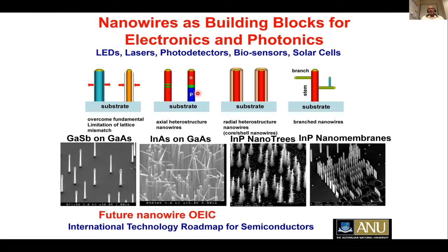You can dope these nanowires P-type and N-type so that you can make PN junctions. Because if you want to make an LED or a laser or a solar cell or a photodetector, you need to have the PN junctions. And by doping different parts of this nanowire with different types of dopants, like in the case of gallium arsenide, for example, zinc and silicon, we're able to make them as a PN junction. So that means we can make single nanowire-based LEDs and lasers, which I will come back to.